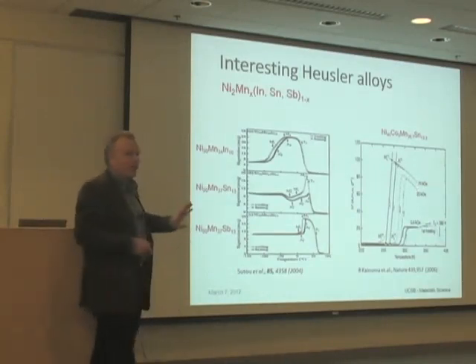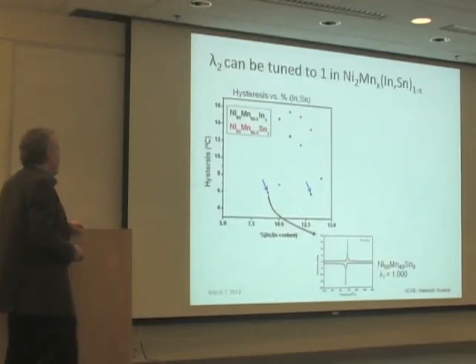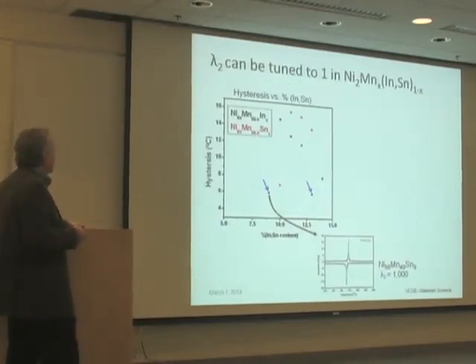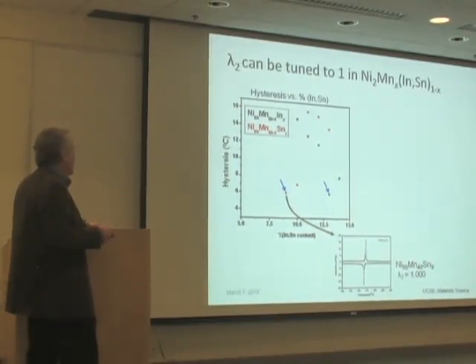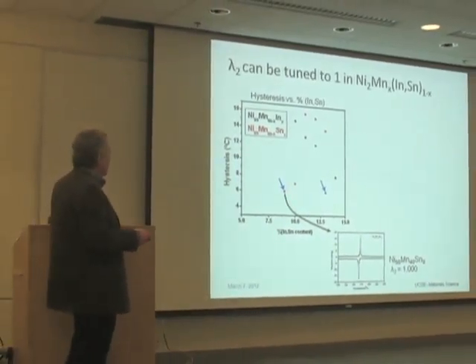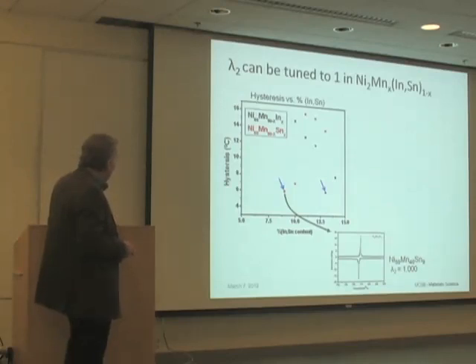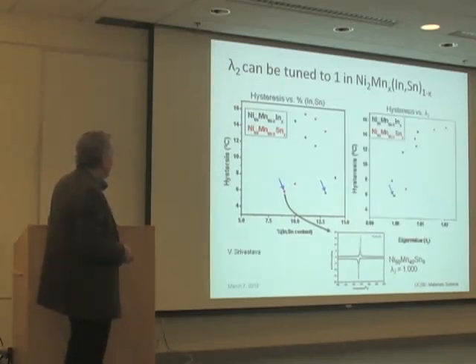And we started tuning. We took the simplest cases, nickel 2 manganese indium, nickel 2 manganese tin, and we started tuning the proportion of manganese and indium, manganese and tin to try to make lambda 2 equals 1. And we achieved that. We didn't do this high resolution tuning, so we have about 6 degrees hysteresis. It was at this composition with the tin and at this composition with the indium. If you replot the data, both of those squares go on top of each other at lambda 2 equals 1. Again, there's a sharp drop. There's a DSC graph, a really nice DSC graph with about 6 degrees hysteresis.